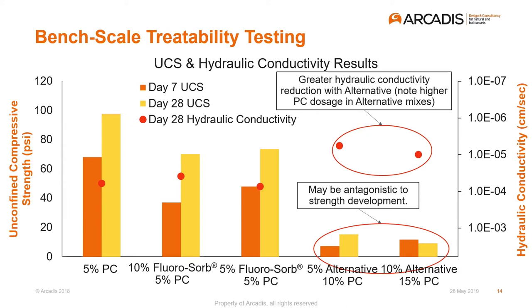in hydraulic conductivity. So if you're going to start looking at leaching of cores that have a confirmed difference in hydraulic conductivity, you've invoked a hydraulic phenomenon that artificially biases these to have a better leachate reduction potential. So we had to modify our 13-15 method to incorporate that, and I'll explain why. I'll explain how in a bit.